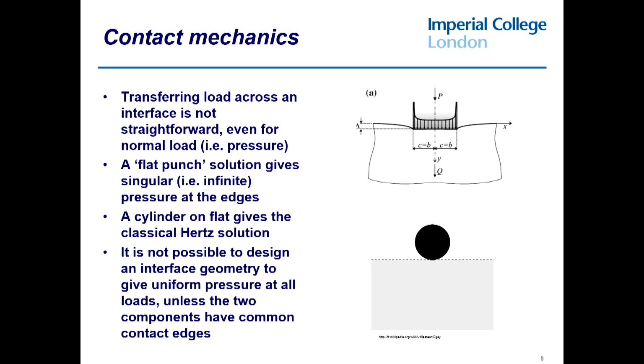If, on the other hand, we take something like a cylinder and we push that down, you will see that you get deformation of the two bodies, but the pressure will be largest in the middle, and it will fall to zero at the end. And it turns out that it's not possible to design an interface that carries uniform load across a range of loads, unless the two components perfectly match, and then you start to wonder why you've got two components in the first place. Okay, so that's contact mechanics.